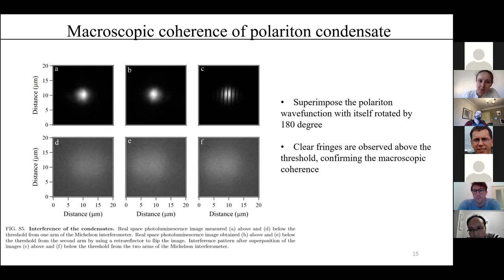Okay, so let me just sum up if I understood correctly. This is the image with the femtosecond laser, so this is pulsed excitation. The excitation spot is large, but you see the signal only from this 5 micrometers. Below threshold, we can see all the perovskite microplate emit light, all of the area; we can collect the PL. But above threshold, we see the condensed area is smaller than the perovskite microplate.